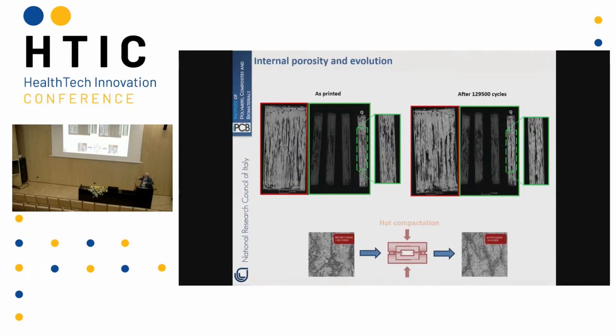This is a microtomography of the sample. You see there is a lot of void inside, about 50% of void. In any case, also changing the printing conditions. The only way that we found to increase the properties of this material is to use a post-processing by hot compaction at high temperature. So after printing, we have to put our systems under pressure to increase the density of the material and reduce the number of voids inside.